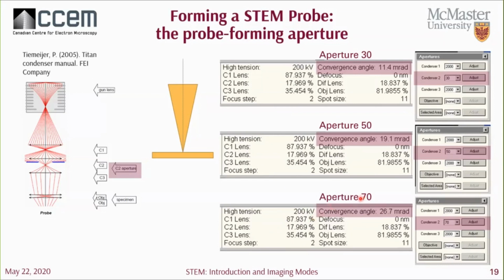So, as I said, our convergence angle is strictly coming from the probe forming aperture. And here is where we see the C3 lens forms a beam which enters the upper objective lens roughly parallel. So note the convergence angle changes depending on aperture size, and the larger the aperture, we get a larger convergence angle and giving you a finer probe.